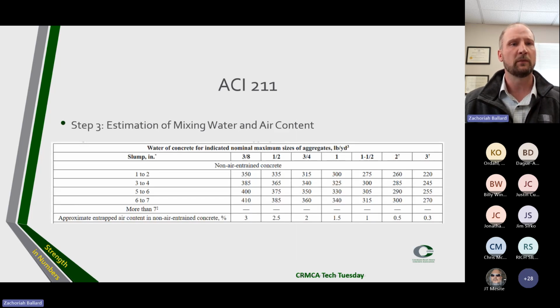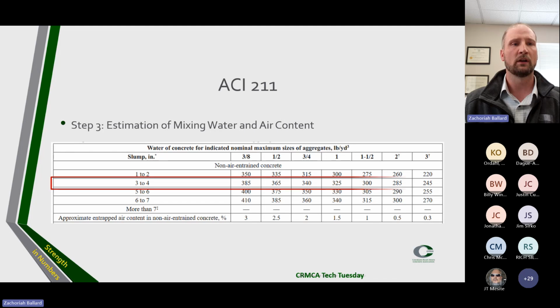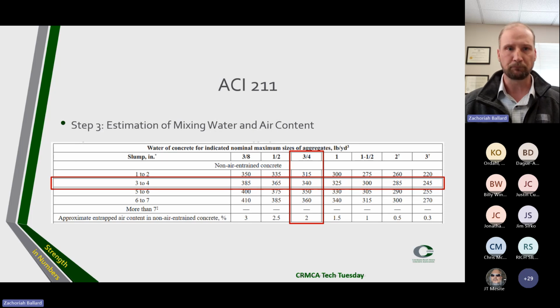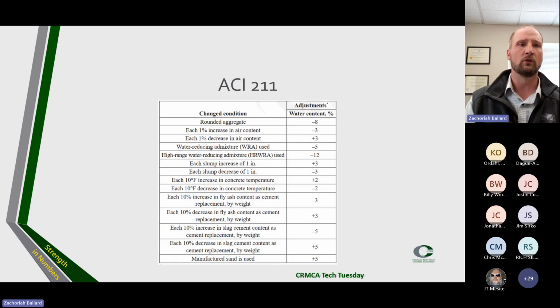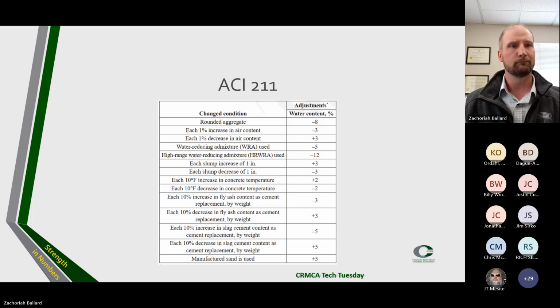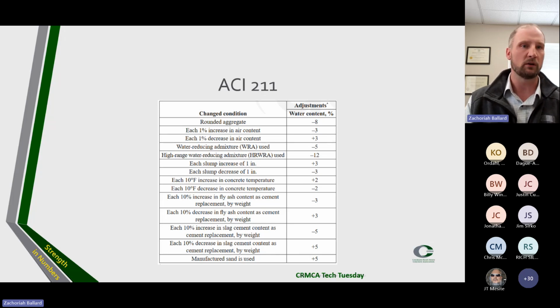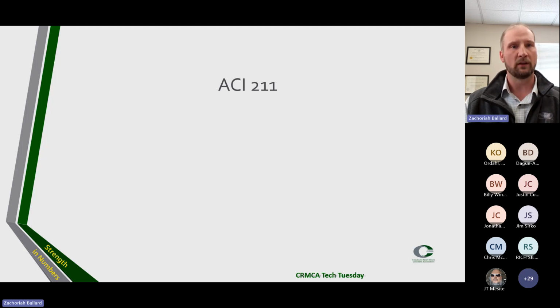So our third step is the estimation of mixing water and air content. So for this example, we're going to do the line here highlighted, the 3 to 4 inch slump with a 3/4 inch aggregate. That's giving us a starting water of 340 pounds per cubic yard. We then go to the next table in ACI 211. This gives us adjustments that we can use for rounded aggregates, increases or decreases in air content. We can kind of go through this chart and adjust our mixing water content based on the properties of the materials that we're working with. For this example, we're not going to do any of those, but know that that's available to us.